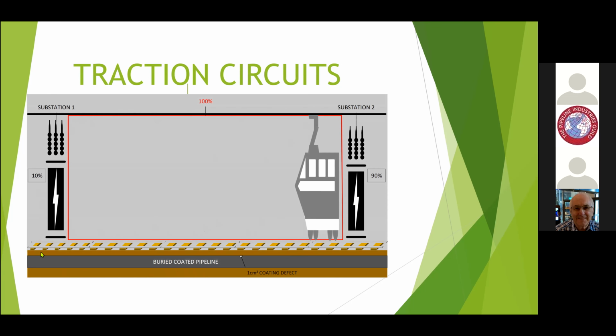So if we imagine a worst case scenario of a long parallel pipe, very well coated, with one small coating defect of 1 centimeter square. And that's a very realistic situation these days, because of the high quality of coatings that you can get now and the high level of supervision and care taken during the installation of the pipe, which means you get very few defects on well-coated pipes that are installed properly. There are always exceptions to this, of course, and that's what pays my wages.